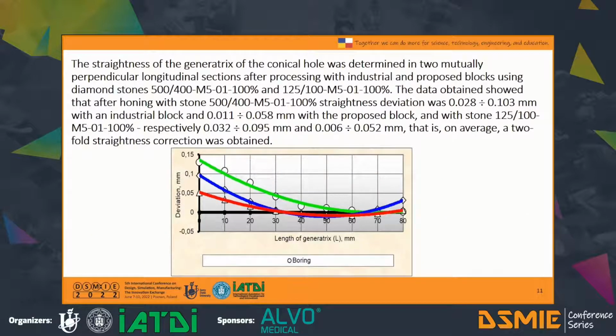The straightness deviations of the generatrix of the conical holes were determined in two mutually perpendicular longitudinal sections after processing with industrial and proposed blocks. The data obtained show that after honing with stone 500-400, the deviation was from 28 to 103 micrometers with the industrial block and from 11 to 58 micrometers with the proposed block, and with stone 125-100, respectively, from 32 to 95 micrometers and from 6 to 52 micrometers. That is, on average, a two-fold straightness correction was obtained.